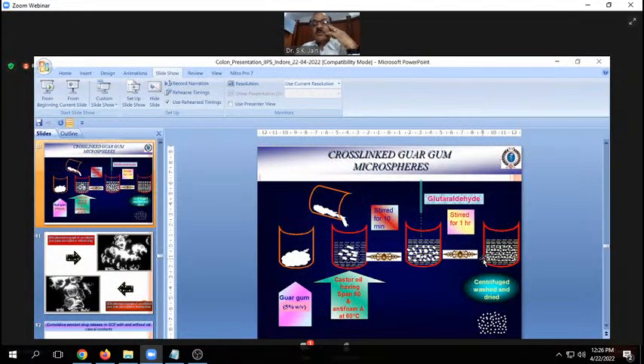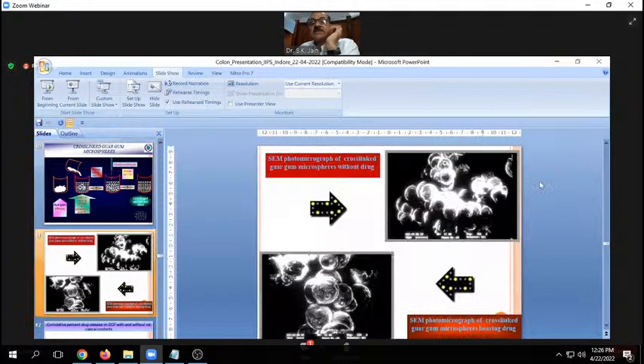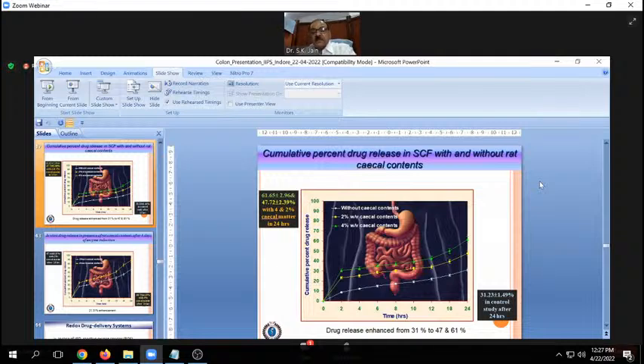Similarly, we can prepare guar gum microspheres using suitable techniques. This is the emulsion solidification technique using glutaraldehyde as a cross-linking agent for solidifying the guar gum. So we prepared guar gum microspheres, and these are the microspheres without drug and with drug. And again, just to see whether these guar gum microspheres release drug in the colon or not, and if so, how much drug is released, and what the effect of the cecal content, microbial content, or enzyme content will be, we performed in vitro release studies in simulated colonic fluid with or without cecal content, and we see that in the presence of cecal content, the drug release is increased.